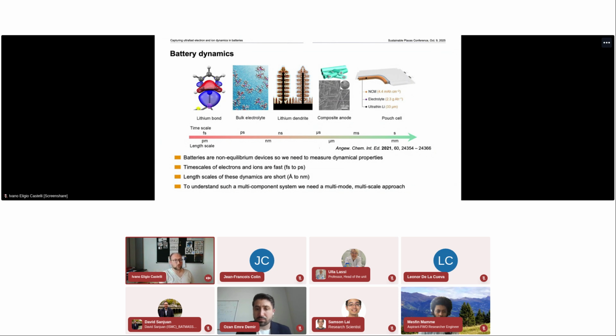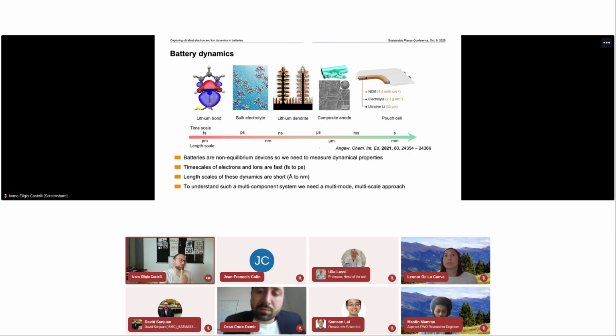So we have effects that happen at the femtosecond or picosecond level and the picometer scale, so typical electron transfer, but then also at the larger scale where the ions move, so lithium intercalating or alloying to the electrolyte or the cathode, dendrite formation, what is the effect on the composite electrolyte, and so on and so forth. So basically what we want to understand is the smallest part of this problem, at the atomistic scale, so femtosecond, picoseconds, where each atom matters, how the electron transfer happens from the electrolyte to the electrode, and the same for the ions.